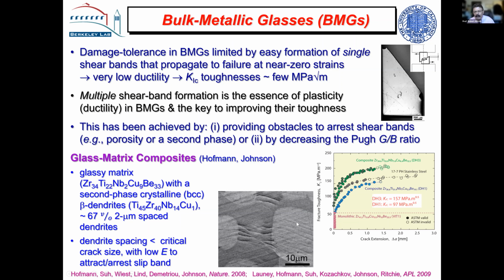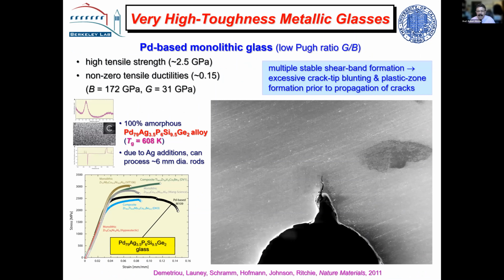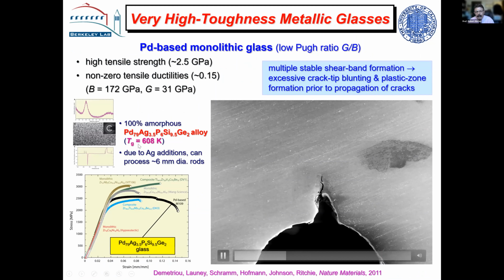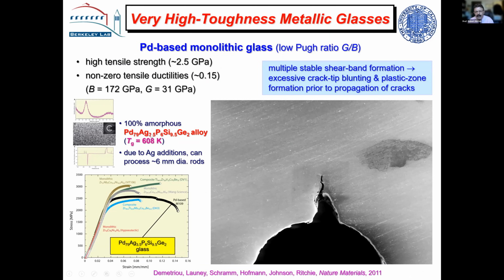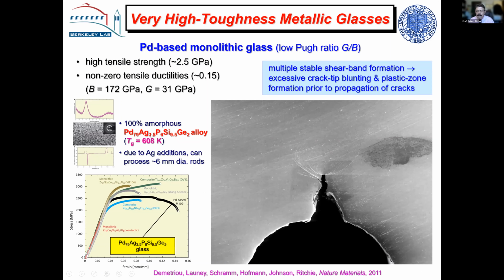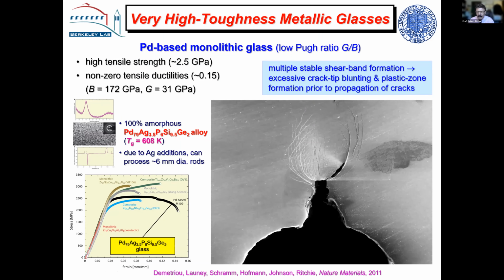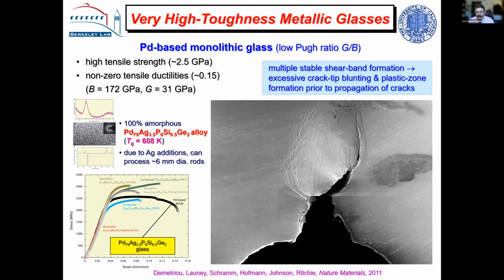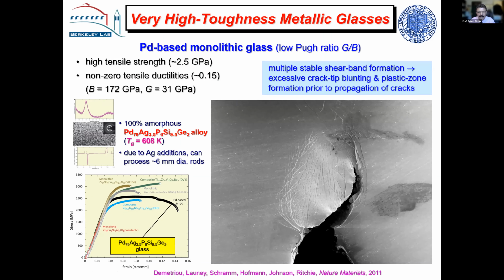So we wondered whether we could do this with a monolithic glass. And this was, again, a while back, but we generated a palladium silver containing glass, which had remarkable toughness. You can see an image of it now. It looks like mild steel. This is a material with a 2.5 gigapascal strength, but it clearly has toughness.